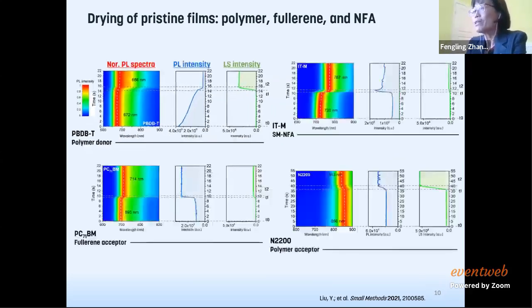And then we also image the 3 acceptors. We can see the difference among the 3 combinations. So for the small molecule, no matter fullerene or non-fullerene, they are red shifted. But for the polymer acceptor, they are blue shifted. And also the PL intensity decrease is different. For the polymer, it decreases faster, and for this non-fullerene acceptor, actually it increases a bit, then decreases. So these different behaviors give us a reference for the blend.